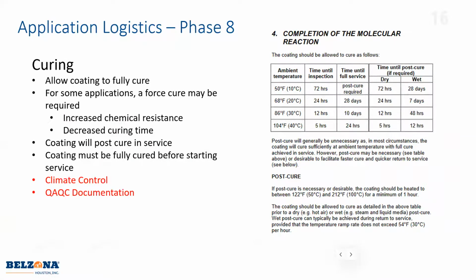And finally, you do it all right. We always tell our clients, just make sure it's cured. I mean, there's no point of going through that whole process and putting it into service too soon. There are ways to make it cure faster via force cure. So for some application we had last year, we put in 150-degree heat with a heater, and we decreased the cure time by almost half. As you can see in this completion of the molecular reaction, you can significantly make your coating cure faster with some added heat.